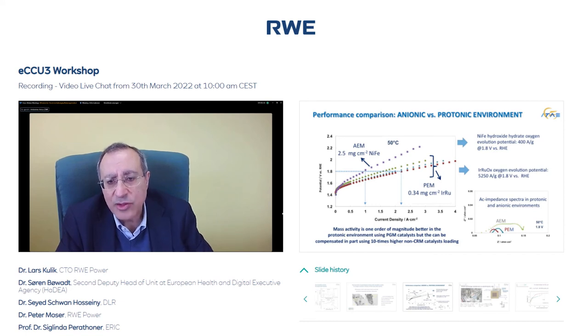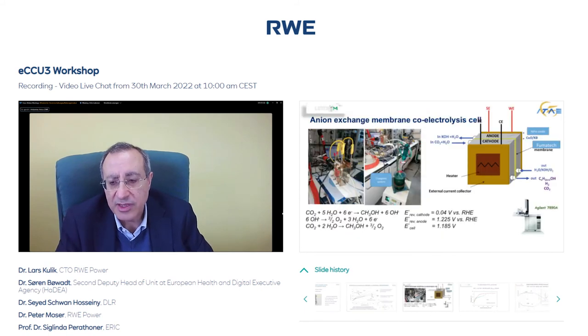However, we can compensate a little bit by increasing the catalyst loading in the case of the nickel iron oxide electrocatalyst, and the performance is still sufficient to get high current density because we have something like 1 ampere per square centimeter at 1.8 volts and 400 amperes per gram mass activity. You can see from the AC impedance spectra that the main difference between the protonic environment based on the precious metal electrocatalyst and the alkaline environment is essentially a significantly larger polarization resistance for the non-precious metal electrocatalyst. So we can move to slide number 15.